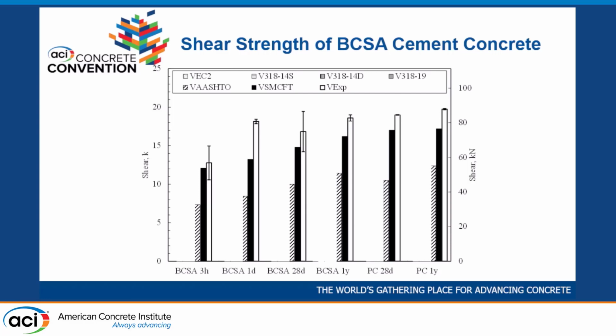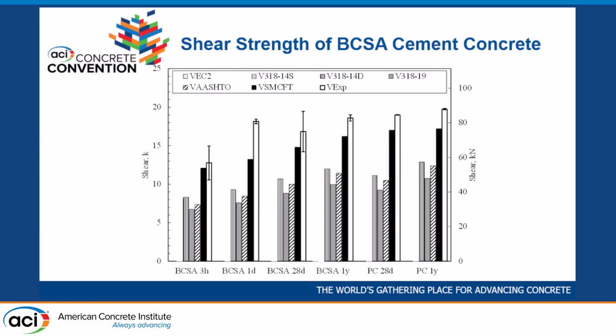This is the simplified method in AASHTO, ACI 318-19, ACI 318-14 detailed, ACI 318-14 simplified, and the Eurocode. If you're not used to looking at shear, all the shear equations are super conservative, so you can see that we're underestimating the capacity by quite a lot. That's sort of by design. And for all of our BCSA specimens, the conservatism is pretty similar to Portland cement. So the equations appear to work the same way for our BCSA cement as they do for Portland.